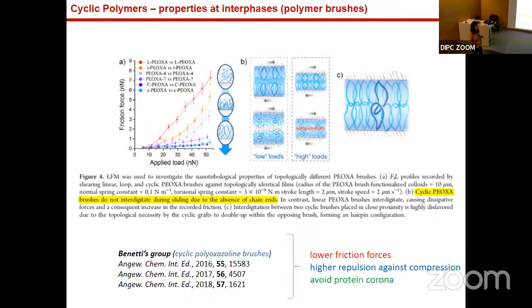Also they measured the repulsion against compression. They compress the surfaces, and they say, okay, our cyclic modified surface shows higher repulsion. Why? Because they observed that the density of polymer on these cyclic surfaces was higher than on the linear ones. So there are many explanations, and it's just thinking on the conformation or configuration of these cyclic structures. And they also measured nanoparticles modified with a cyclic polymer, how they behave in the presence of protein, and the cyclic brushes avoid the formation of a protein corona, for example.